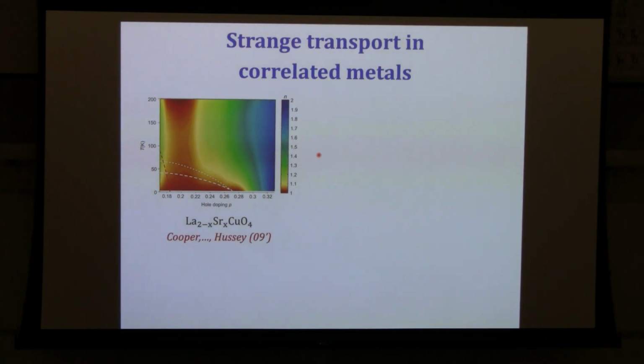So what I'm going to talk about is a different phenomenon. This is a similar plot as before, for a hole-doped cuprate. It's a high temperature superconductor, and again, what's plotted here is a phase diagram. This axis is doping, so basically the number of carriers doped into the system, and this is temperature. And what's plotted is, again, the exponent of the resistivity as a function of temperature. It's basically the log derivative of the resistivity with respect to temperature.